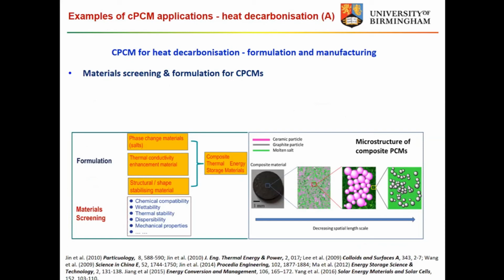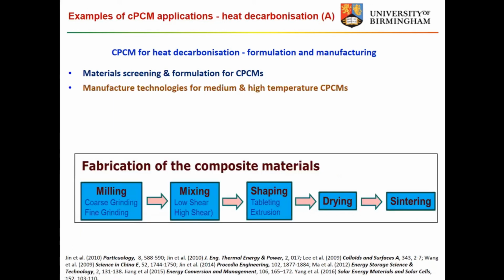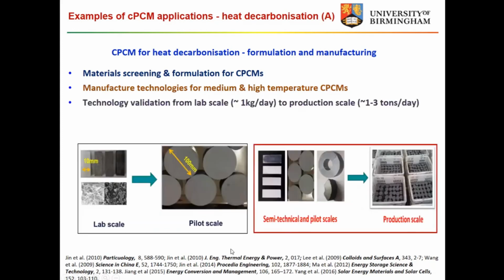From material screening, you have to have different materials which are compatible physically and chemically, with good dispersibility when you mix them, and when you produce those, you have good mechanical properties. Essentially, you have a skeletal material, and a heat transfer enhancement material dispersed in phase change material, which form the microstructure and shape-stabilized module. Of course those also cause manufacturing issues. One of the methods we've been developing is used in conventional food production, minerals, detergent and pharmaceutical industries: mixing, shaping, drying, and sintering. Those are examples from lab scale to pilot scale, and from semi-technical to production scale.